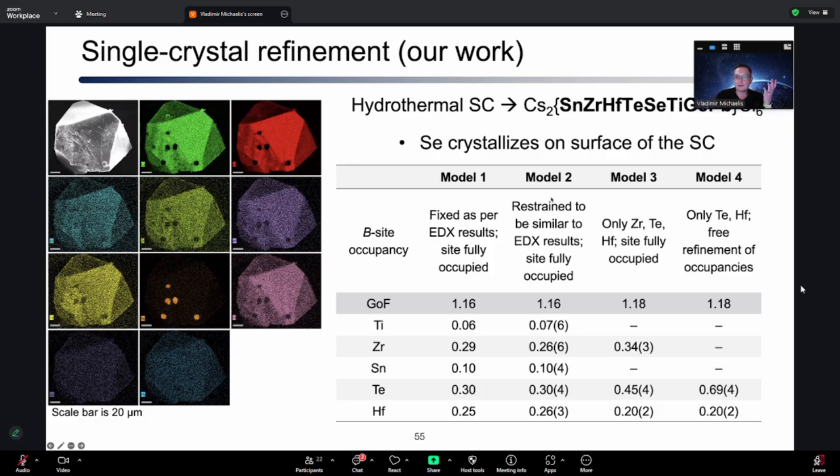If you take these materials and do a full single crystal refinement, what ends up happening is, because you have so many isoelectronic metals in an isostructural system, you actually can fit them to anything. For anybody that's really an expert in diffraction, this isn't shocking to you. But if you didn't know this, it happens quite frequently.